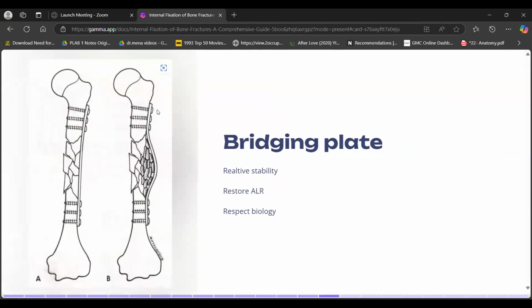The bridging plate is a sort of relative stability. We use the bridging plate for comminuted fractures. This will help us to restore the alignment, the rotation, and the height as much as possible. And it also respects the biology of bone, because it is not causing that much damage to the already broken area.